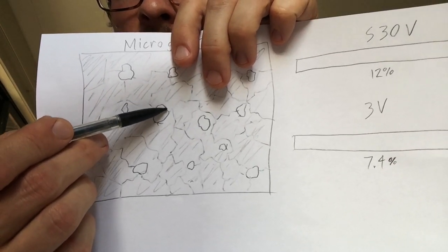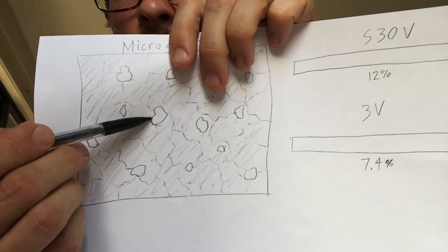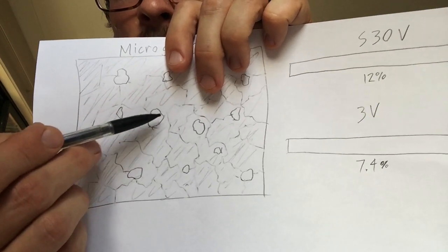once it forms, it will begin to suck in chrome from all the steel surrounding it, and it will actually rob chrome out of the steel solution or the steel matrix, which will actually then drop. You're adding chrome to make it more rust resistant, but as it begins to form carbides, those carbides actually have a localized drop in rust resistance, so it counteracts its own positive effect, if that makes sense.